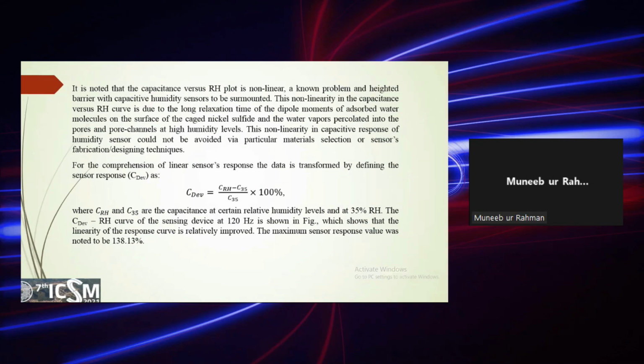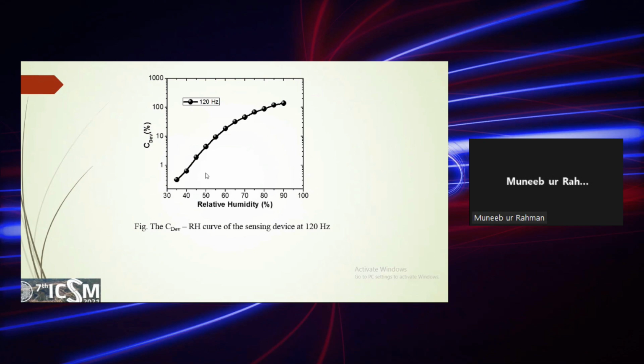There is a problem normally with capacitive type sensors: the behavior of the sensor is not very linear. For this purpose, we transform our data by defining the sensor response, using a formula reported in the literature, where C is the capacitance at some elevated relative humidity, and C35 is the capacitance of the sensor when the humidity was at 35% RH. This shows the capacitive response of the device, which is very linear up to 60%, and then deviates from linearity above 60% relative humidity.